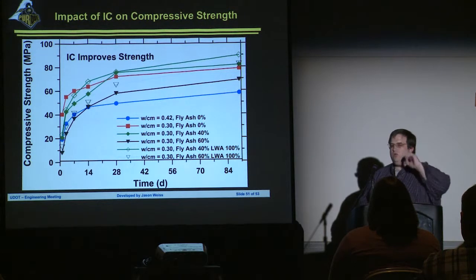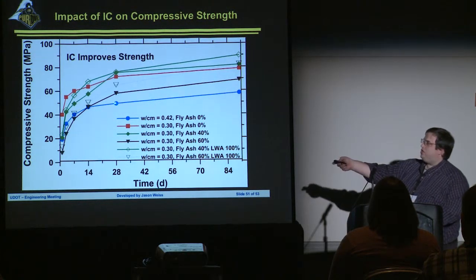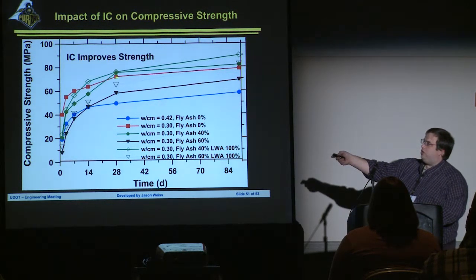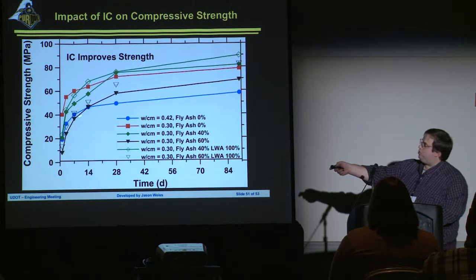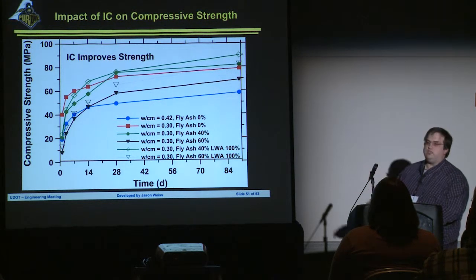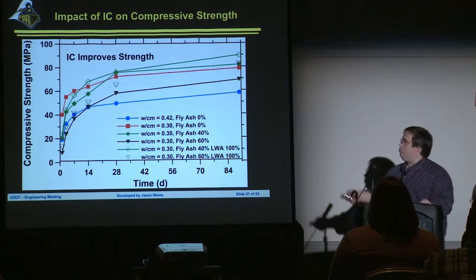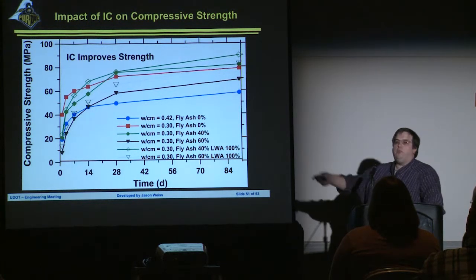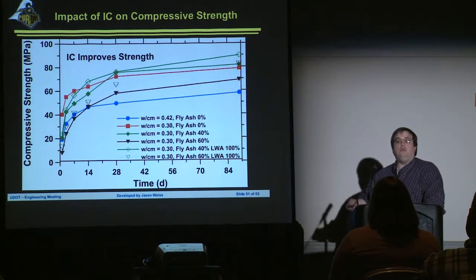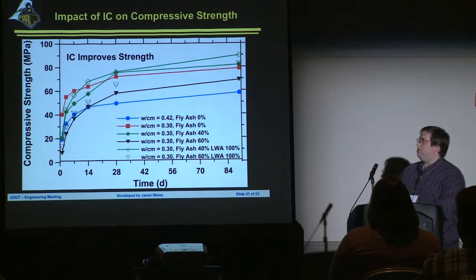Now you may say, well, what is all that doing? We're essentially lowering the water to cement ratio, but then replacing a lot of the cement, so we're maintaining similar strengths at early ages. We use internal curing, and that helps us to bump up the strength because we're getting more hydration of that fly ash, more hydration of that cement in the overall system.